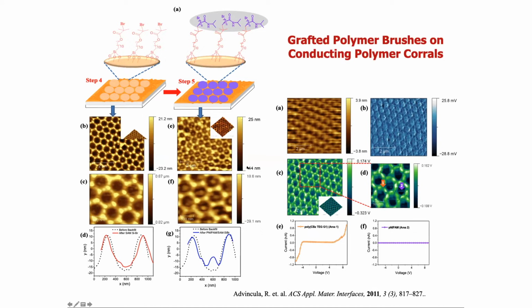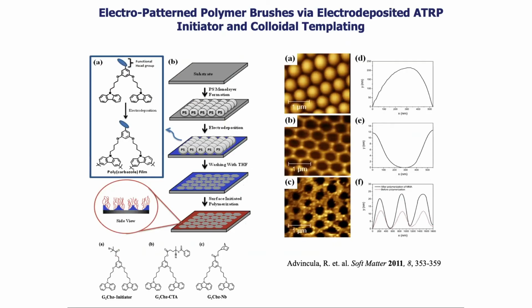Now, to visualize the difference between the conducting pattern and the non-conducting polymer brush, we were able to use a conducting AFM or current sensing AFM to distinguish between the IV current on the conducting pattern colored green and the non-conducting polymer brush colored blue. So this is a good way to combine electrochemical information with AFM.